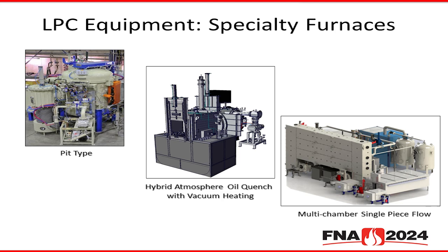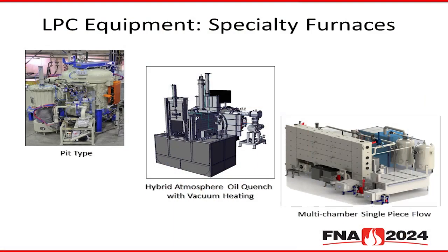And then, of course, there are some other more specialty type scenarios. One is a pit type vacuum carburizing furnace, obviously for more massive parts, that can be arranged with a traditional oil quenching or water quenching setup. The furnace can be opened hot so we can remove the part, move it to the quench chamber, quench, and then reload the furnace at temperature. The difference here is that it's a fiber lined furnace with metal heating elements.